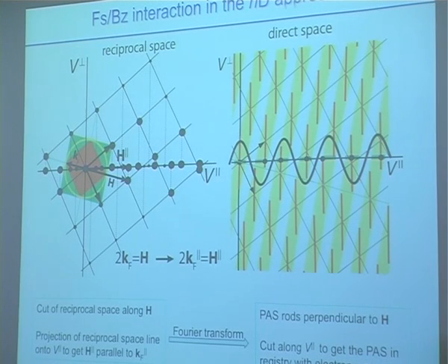And this means in direct space that you clearly have electronic wave related to the Fermi energy, to the wave vector Kf, and you have, of course, then here the periodic average structure, and it's one way to describe this Fermi surface Brillouin zone interaction in higher dimensional space. It works quite well. If you do it in physical space just, then you have your Jones zone. It's completely equivalent. So this is a higher dimensional description of this Jones zone approach.